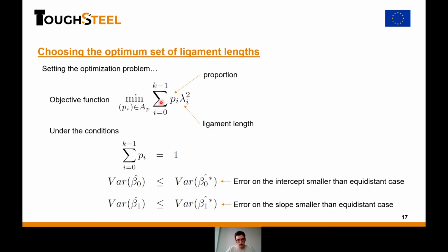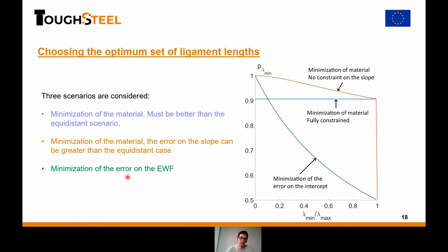And finally, I remove this objective function, and instead I use this one as an objective. So I want to minimize the error made on the essential work of fracture. In this case, what we realize is it's the same. We still want to have more and more samples that have as ligament length the lower bound of ligament length. Typically, for instance, the smallest ligament length possible for me is 5 millimeter, and the highest is 25, so we would be at around 0.2. And so I would have around 85% of my total number of samples with this lower bound of ligament length.